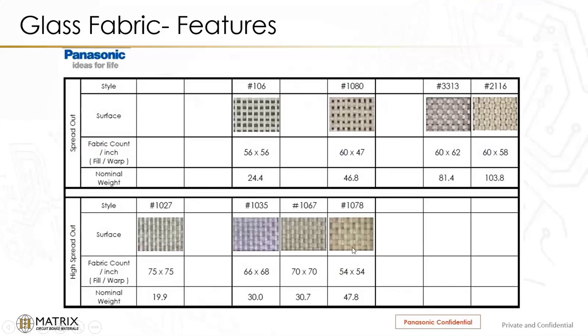So really the high spread, the ultra spread glasses here, the 1027, 1035, 1067, 1078, these are all the glasses that were considered the ultra spread or high spread glass, and they're really optimized for that because of the number of yarns. They're balanced in X and Y. 1035 has a balanced weave with 66 by 68, and 1078, 54 in each direction. But the reason why they're in these columns is because a 1078 is very comparable to a 1080, and we'll look at the thickness and the weight, which are very comparable. The same thing for a 106 and a 1035. The 1035 replaces the 106 in both Meg 6 and Meg 7, because of the thickness of them and also the weight. So that way it can be very comparable in the stack up.